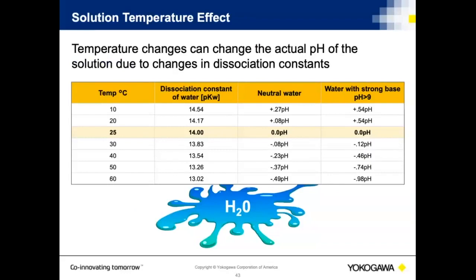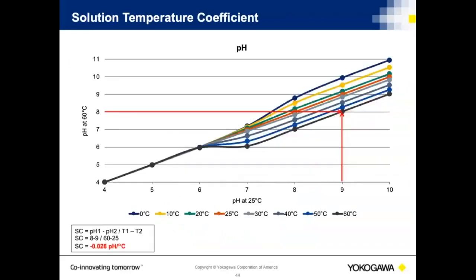So it is a repeatable phenomenon. I can look at the disassociation constant at 25 degrees C, and you note that it's 0 pH. But at any other point, you will see a variation in the actual dissociation constant, as well as how much it affects the pH. Just another illustration down at the bottom. The point being pointed out in the diagram indicates a solution temperature compensation that will affect the measurement at a rate of negative 0.028 pH per degree C.